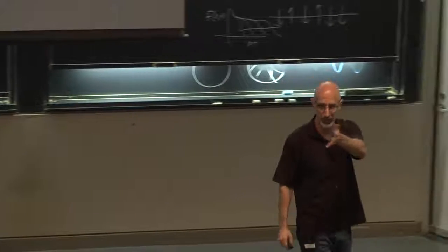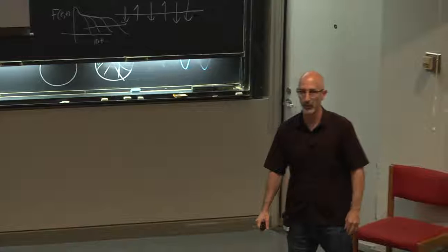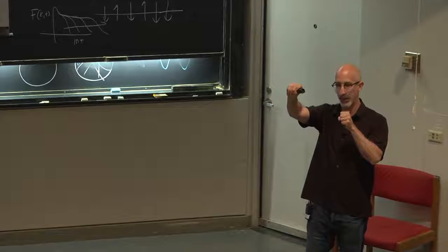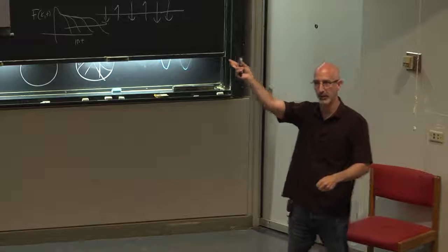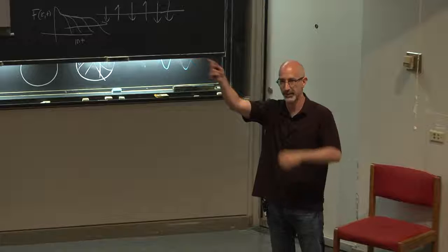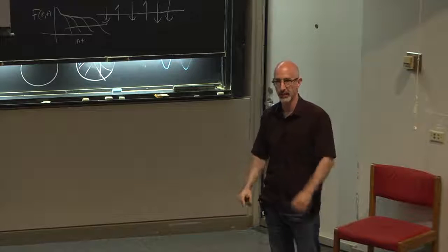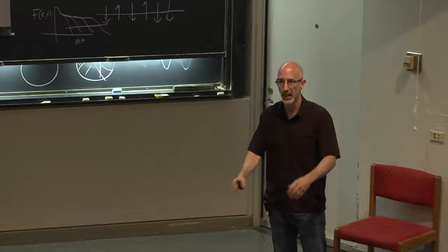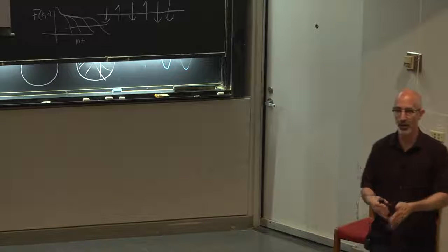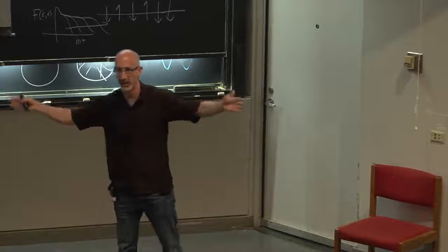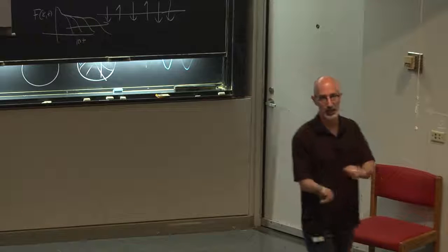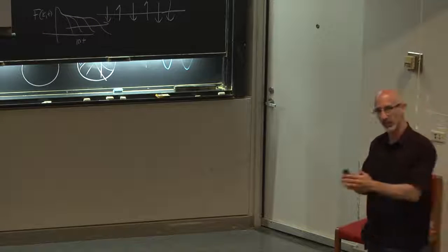It's also true that there are 3-dimensional models where you can see this. One is a very nice model of Mari and Kurchan, where you take, let's say, pairwise interactions of particles, but on top of Ri minus Rj, you can give a random shift to the particles over any distance scale. You have a distribution of these random shifts. If you take the width of this distribution as 0, you get back your regular hard sphere system. But if you take that width to be very, very large, you have more and more of a mean field-like system. And you can tune this by hand from this distribution.